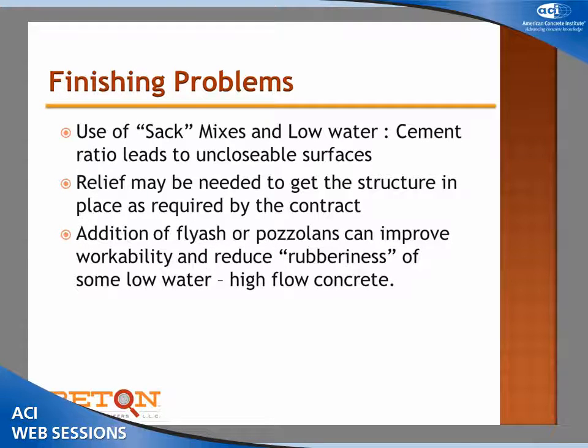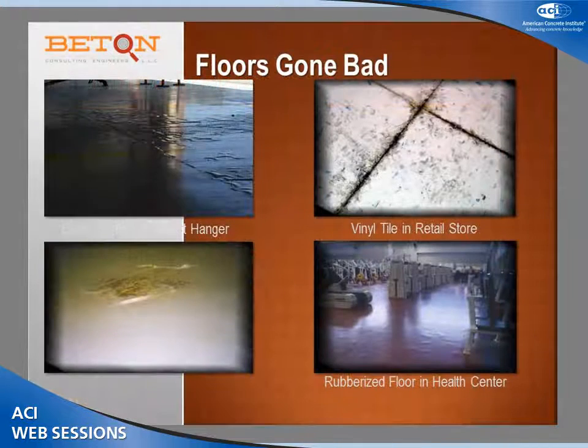We got lots of finishing problems, and they come from all sorts of other places. And then we have this discussion. I had these slides prepared before the responsibility meeting, but this is an issue that occurs very much, and the fellow left holding the bag, unless he can blame it on his material suppliers, is the ready mix operator. Because you say, well, your concrete has a pH of 12.5, and I said, that's because I put the Portland cement in that you specify. So you end up with this situation, who's to blame here?